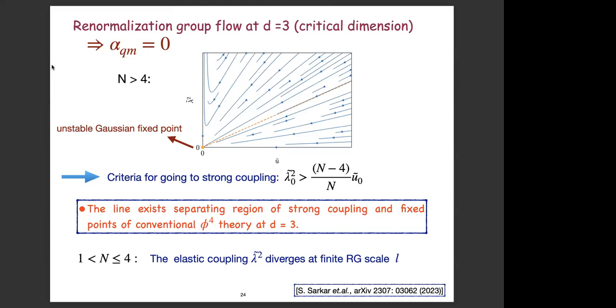What we see is that we have an unstable Gaussian fixed point because the flow is away from this point here, both along the u and lambda axis. And if you look closely, this separatrix which we saw earlier exists, and you still have this stable Wilson-Fisher fixed point, but in this case, the Wilson-Fisher fixed point actually moves towards this Gaussian point, basically merging. So all the flow looks like it's going there. And above this regime, the flow is again towards strong elastic coupling. So it goes in there, but then it diverges if you're closer to the Gaussian or the Wilson-Fisher point here.